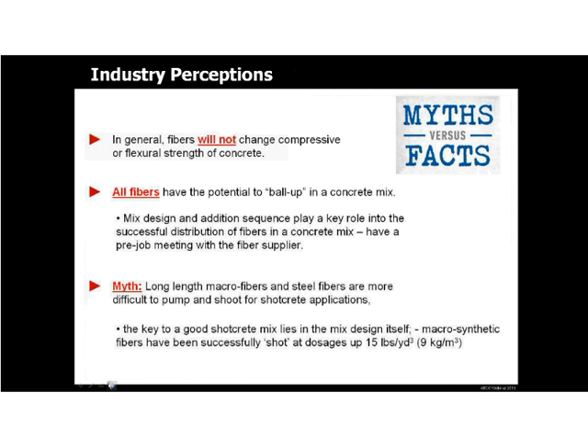In terms of fibers balling, seeing watermelons and baseballs and footballs rolling off the back of a concrete chute, there are no fibers within the industry that do not possibly ball up in concrete. But the key to those is to work with your ready-mix producers. If fibers are to be used, how they add those fibers, where they add those fibers is extremely important. And the three most important words that will go a long way to alleviating those potential problems would be simply a pre-job meeting. Discuss that with your producer, that fibers will be used. Ensure that they're not allowing the slump of that mix to go below 2 inch at any time during the batch sequence when adding fibers or admixtures. And have that concrete delivered on site with the fibers properly distributed within the concrete.